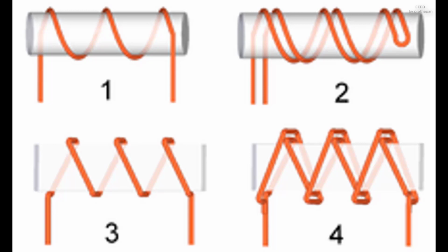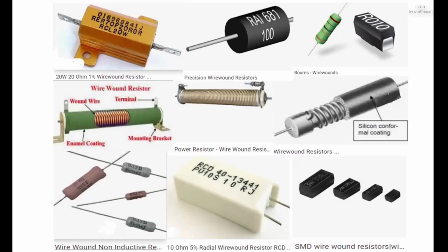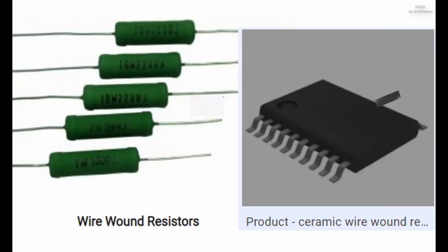4 Ayrton-Perry. Wire wound resistors are commonly made by winding a metal wire, usually nichrome, around a ceramic, plastic, or fiberglass core. The ends of the wire are soldered or welded to 2 caps or rings, attached to the ends of the core. The assembly is protected with a layer of paint, molded plastic, or an enamel coating baked at high temperature. These resistors are designed to withstand unusually high temperatures of up to 450 degrees Celsius.